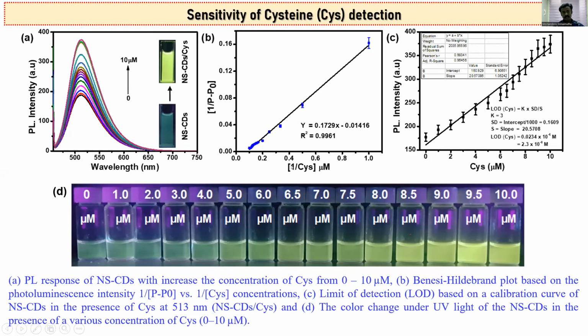In the micromolar range, we can get the linearity from this, with an R square value of 0.9961. So we can confirm from this plot the complexation. This complexation is the carbon dot and cysteine molecules forming a 1:1 complex ratio.